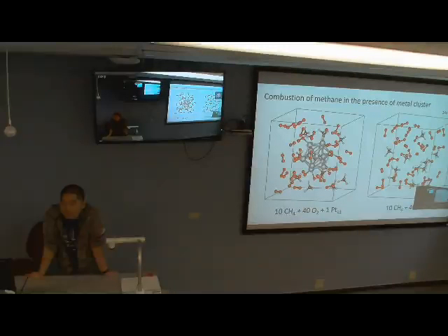So if hydrogen abstraction is usually the first chemical reaction, how would platinum help catalyze that? Because it'd still be dependent on the methane losing a hydrogen. And I would assume it's going to be mostly oxygen interacting with the surface. We can adsorb the methane on the platinum. Or they both can adsorb, then the probability of them being next to each other would dramatically increase. And then it can facilitate the reaction.